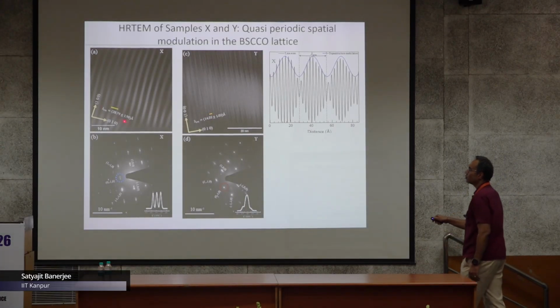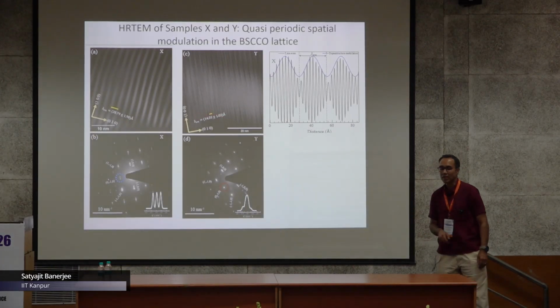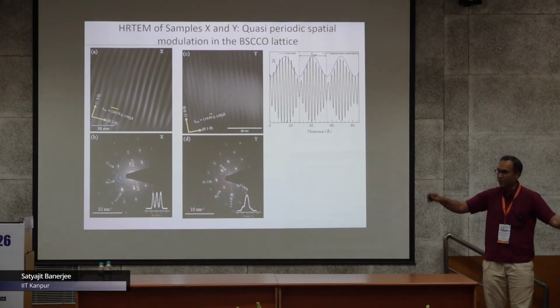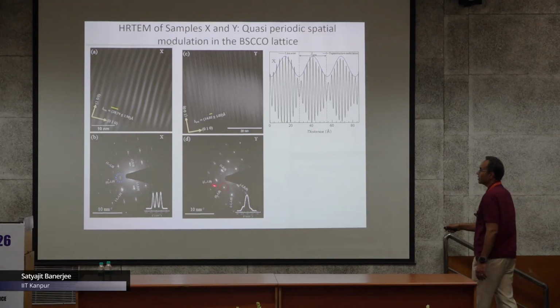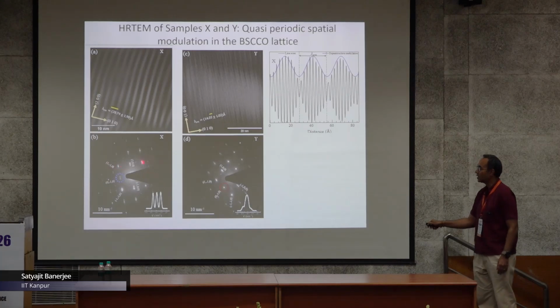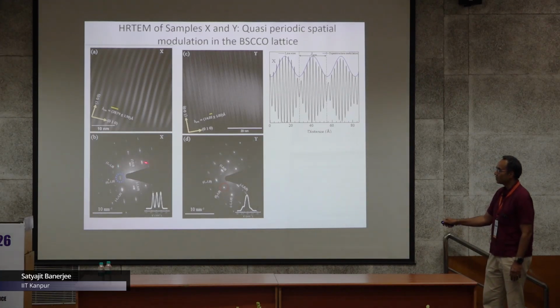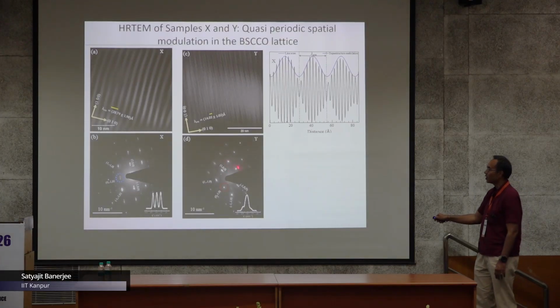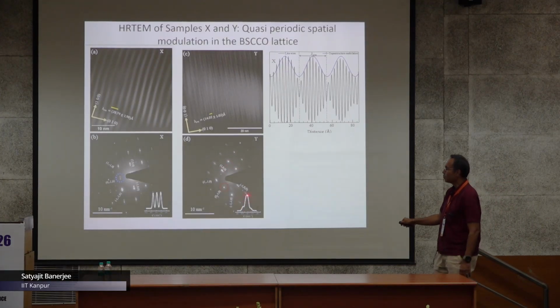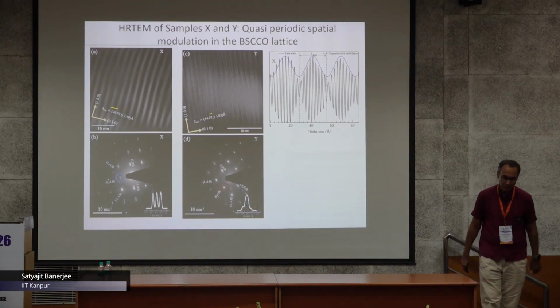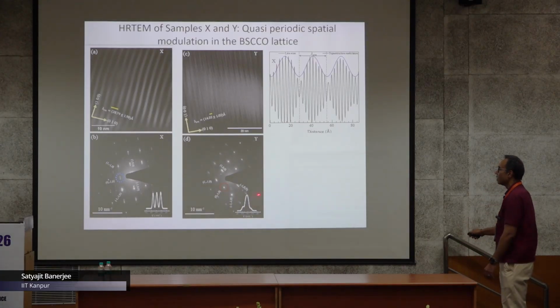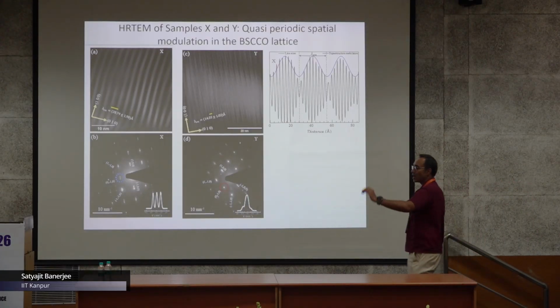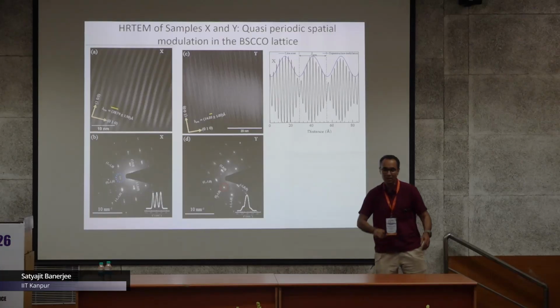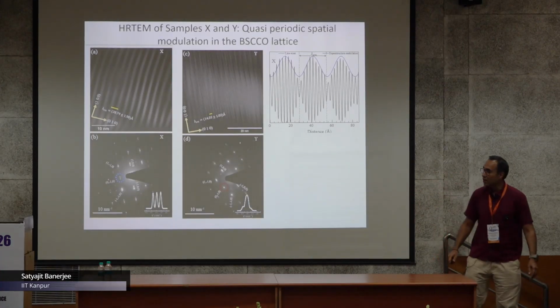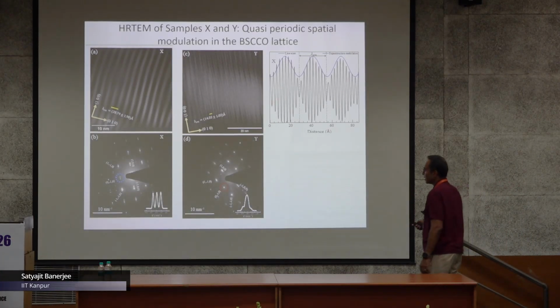This modulation from 28 nanometers has come down to 14 nanometers, and it is not uniformly present all over the crystal. The spots that were each surrounded by 3 other diffraction spots have now mostly gone in most places, though present in some. The full width at half maxima of these spots is pretty big, meaning it does not have very high long range order—these modulations are not present over a very large distance inside the system.